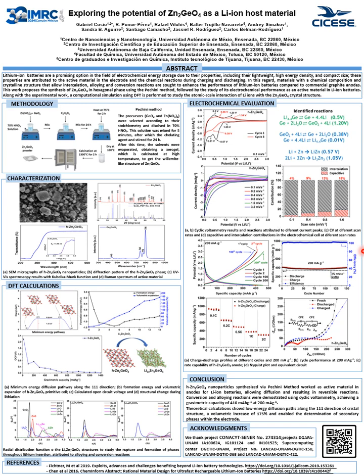An increase in capacitive contribution with higher scan rates was observed, as higher speeds provide less time for ions to insert into the structure and react. A galvanostatic cycling process was conducted. The first figure illustrates the charge and discharge profiles at different cycles and a current density of 200 mA per gram, showing capacities of 410, 378, and 450 mAh per gram for the first, 100th, and 200th cycles, respectively.